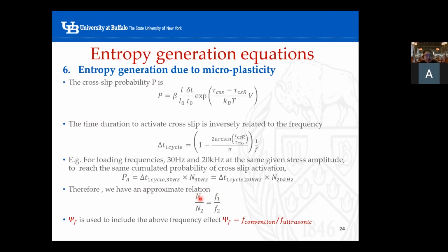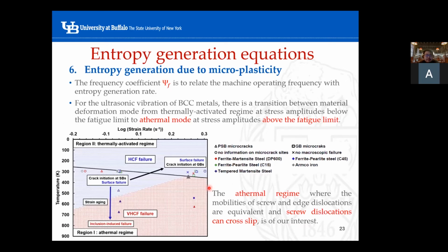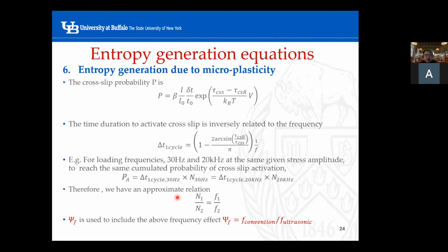The number of cycles to reach value is positively related to the operating frequency of the testing machine. But this equation only applies to ferrite-based metal, because for ferrite-based metal we have this kind of transition mechanism and this kind of cold duration quantity. So that is restricted to that case.